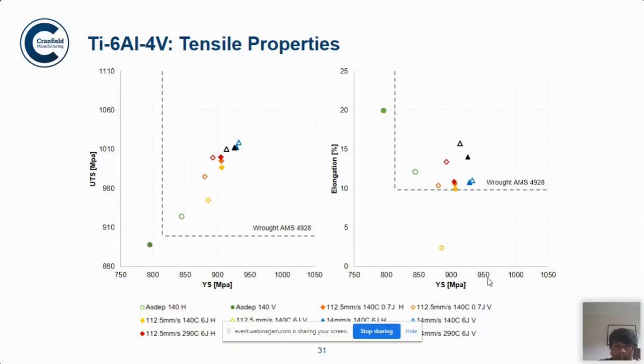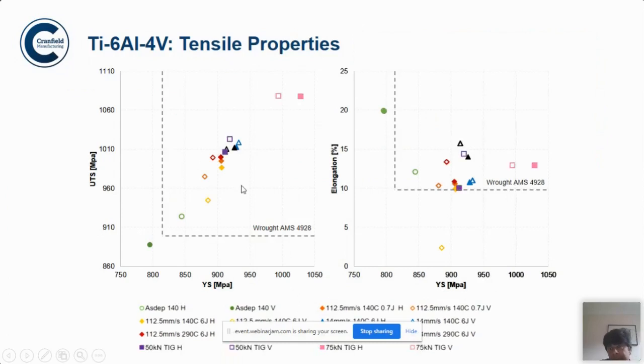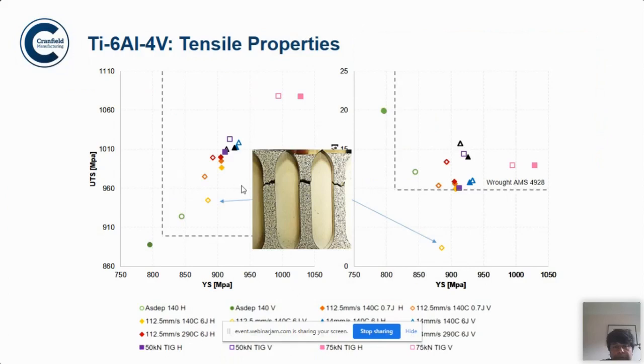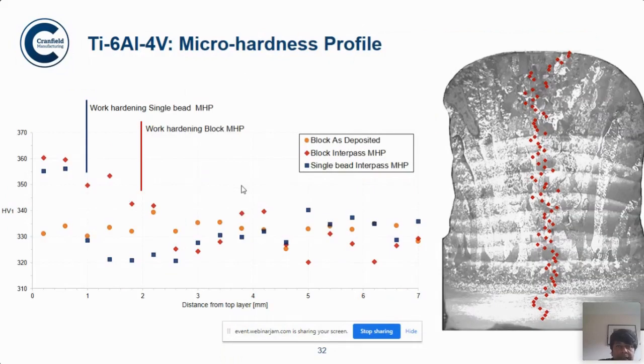Property wise, once again, just concentrate on these green ones here. The green ones are the as deposited ones, which are much lower, and the rest are peened. You can see that the property has moved up substantially, both in terms of UTS and YS. This is some more examples of doing a hardness map and showing that when you peen, your hardness goes up, which basically indicates that it is strain hardened. This is quite natural, and because of that, you're getting the recrystallization after laying the next or the following bead.